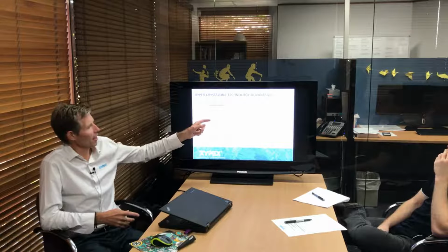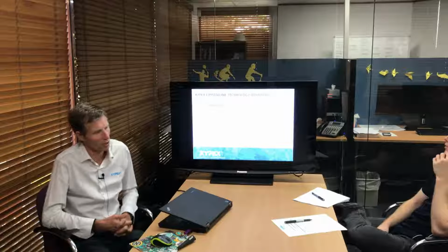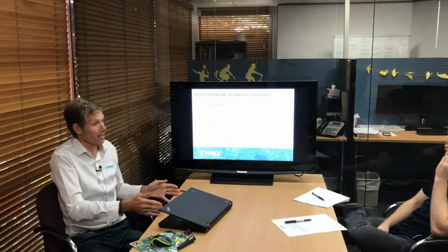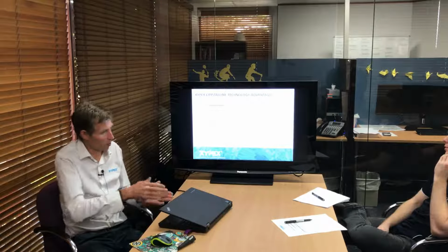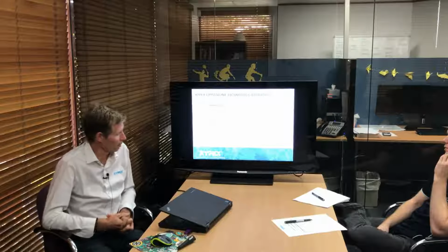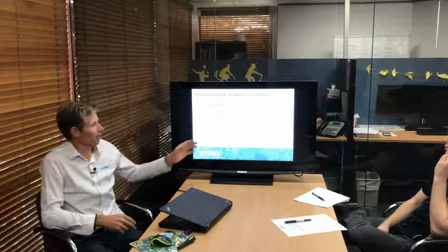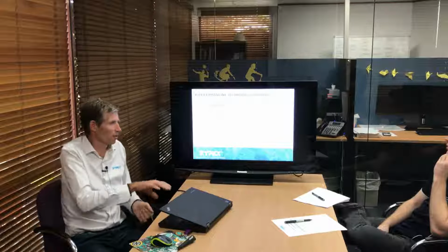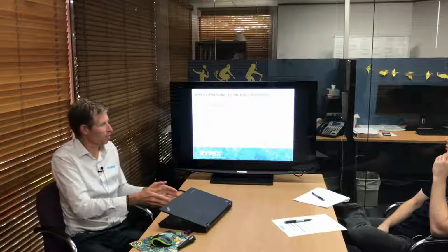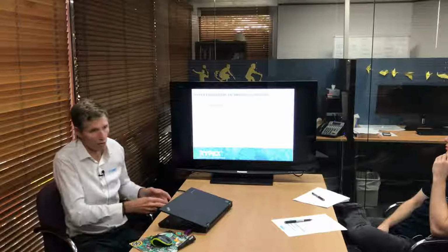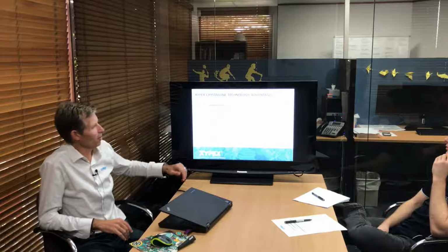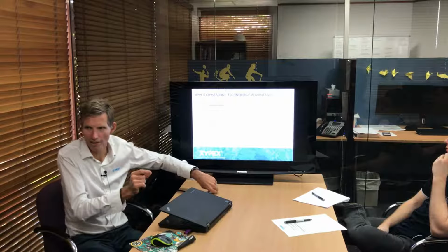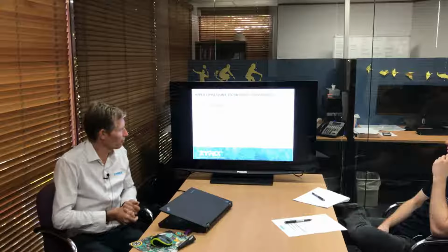Now, this is quite a key one: increased early and later age strength of concrete. A lot of that is representative of the concrete mixes themselves, but against those mixes, we do show improvements. Depending on the concrete mix, that can vary from about 10 to 20%. If you've got a 32 MPa concrete, we would probably see a better early and later age strength near 20%. When you're dealing with a 40 or 50 MPa concrete, we're probably seeing an improvement in strength gain near 10%.